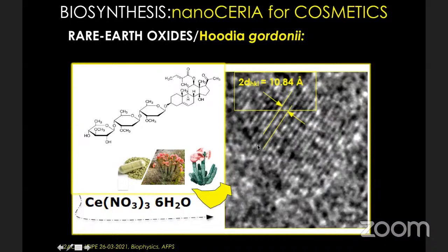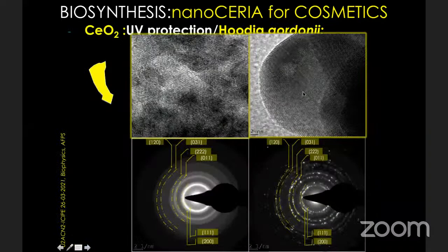As you can see, this is a high resolution. You can't have better, at least in South Africa with our attempts. You can see clearly that you have a quantum dot, a nanocrystal surrounded by amorphous, and this is a cerium oxide. As you can see, this is a bar of 2 nanometers. This is amorphous, a very small amount, and these are very small crystals. This is a little bit larger crystal, so this is highly crystalline.